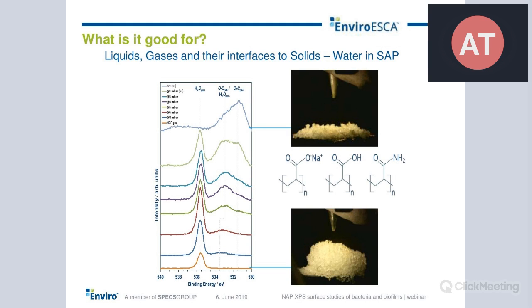And of course, it is also a pretty nice tool to measure liquids, gases, and all their interfaces to solids. And this is shown here by a water-soaked superabsorbent polymer, where when you are far away from the entrance of the analyzer, you only see the water vapor signal, so that's the oxygen 1s signal. So you see here water vapor. When you then come close into the measurement position, you see besides the water vapor also the absorbed water inside the superabsorbent polymer, and then you can start to dry out the superabsorbent polymer, where it shrinks until it is completely dried in this stage. And you see that the portion of the absorbed water that you can see in the spectrum is increasing. And finally, you also see increasing the oxygen-containing groups of the superabsorbent polymer, so that you really can learn how water or liquids are incorporated and absorbed in porous materials.